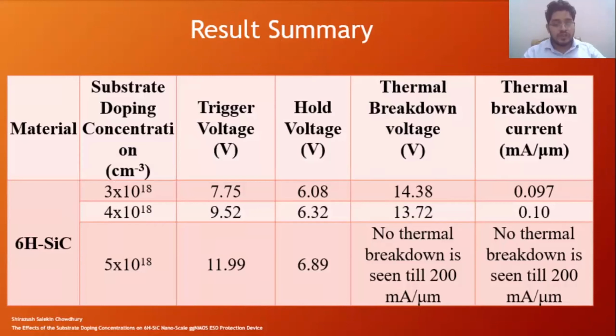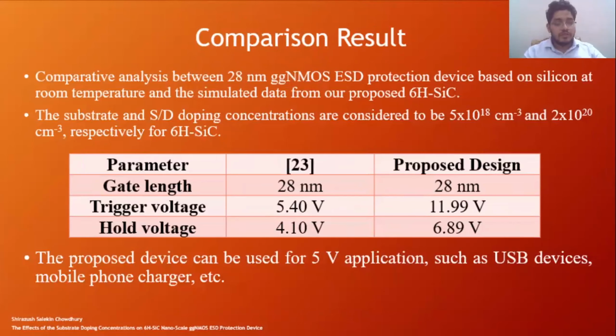For the doping concentration of 5E18 per cm cubed, no thermal breakdown is found up to 200 mA per micrometer. The table shows a comparative analysis between a 28 nanometer GGNMOS ESD protection device based on silicon at room temperature and the simulated data from our proposed 6H silicon carbide. The study shows that the minimum hold voltage of the GGNMOS should be 1.25 times the normal operating voltage of the on-chip circuitry.